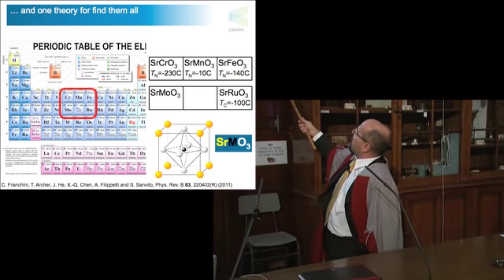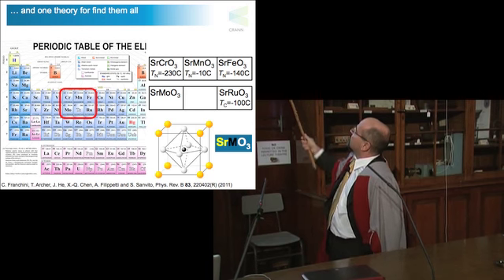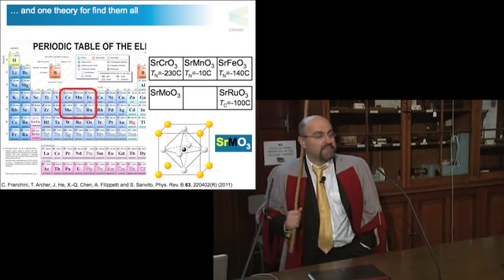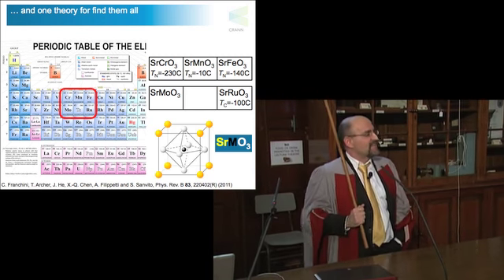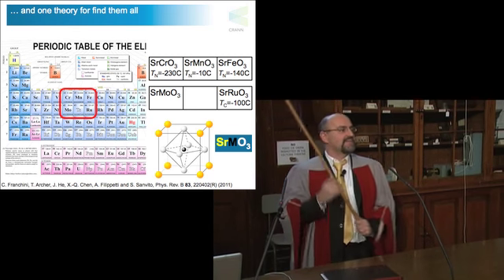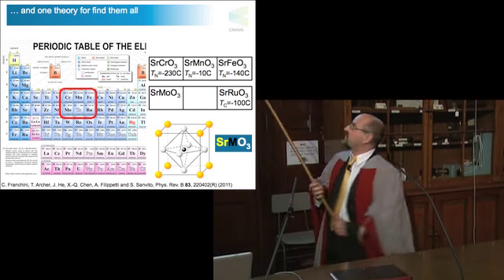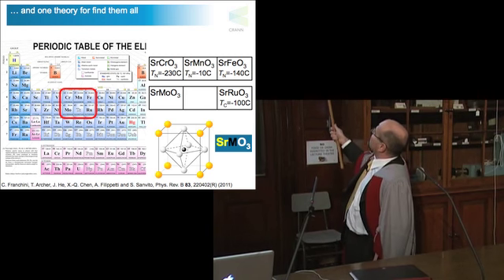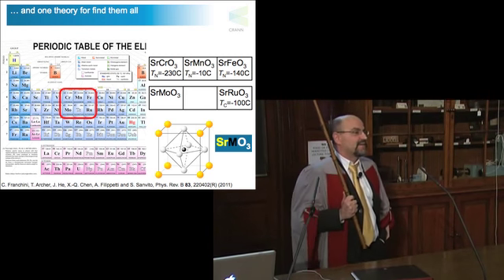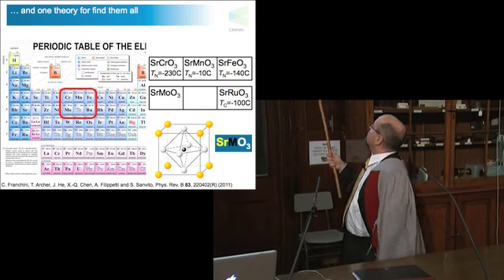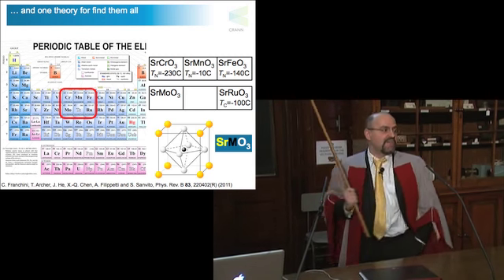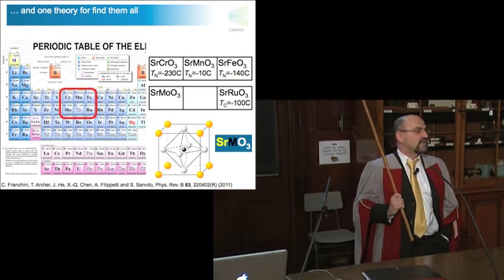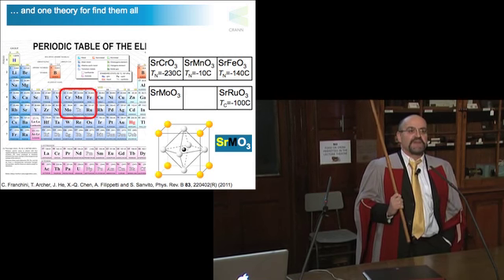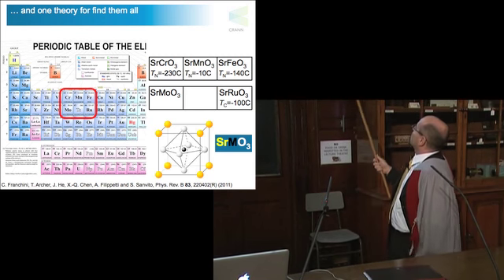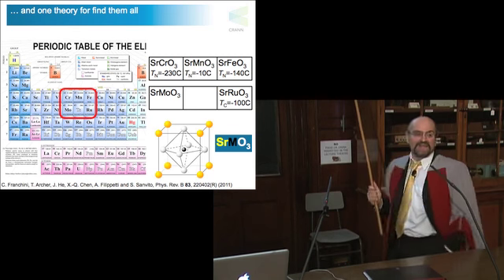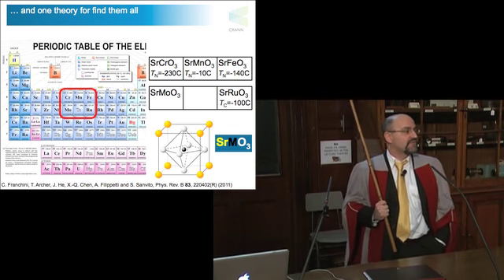If you take manganese, you have strontium manganite, and this is also a magnet, but at minus 10 degrees. So this is not too bad. It's a magnet in the winter. It doesn't become magnetic in the summer. Then you have strontium ferrite, also quite bad, minus 100 or so. Strontium molybdenate is never magnetic at all. So you can cool it down as much as you like. Nothing is ever going to happen. Strontium ruthenate, magnetic, but at minus 100 degrees, so not very useful either.